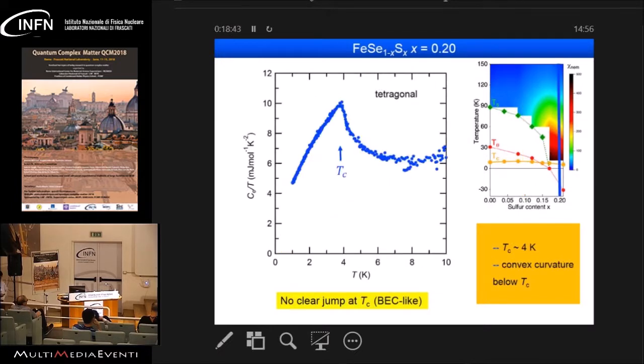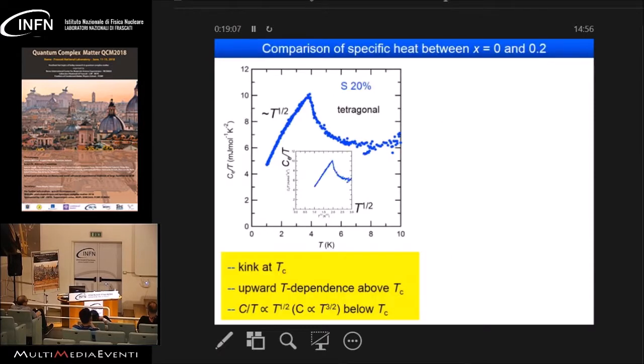However, we were very surprised to look at this data, which is at 20%, which is on the tetragonal side. Okay, so we have no nematicity here. Okay, and so C over T shows a gradual increase towards Tc, and shows no jump, but we have a kink at Tc. And if you plot the C over T as a function of square root T, then we get a straight line below Tc, meaning that here we have a temperature dependence of square root T.